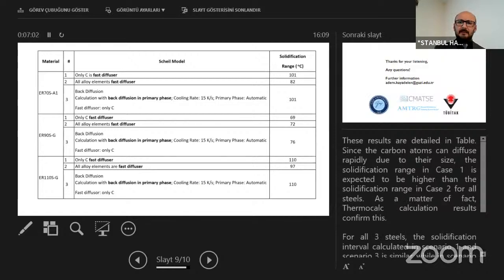This is the results table. These results are detailed in the table since carbon atoms can diffuse rapidly due to their size. The solidification range in case 1, where only carbon is the fast diffuser, is expected to be higher than the solidification range in case 2 for all steels. As a matter of fact, the thermal calculation results confirm this.